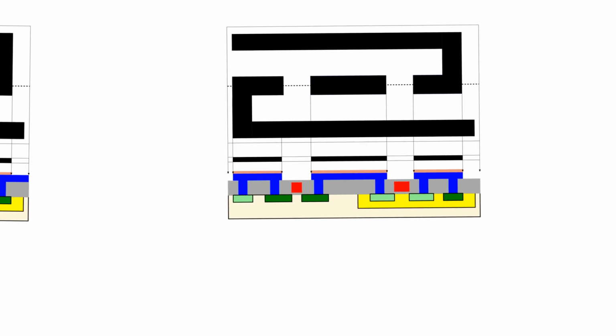We can then use etching to eat away at the metal layers. If we are using aluminum as the metal of choice, then we can use dry etching to eat away the areas that were exposed. Dry etching is actually very good because it is directional, it does not eat laterally, but there's a problem with it in that it builds up a lot of static charge, which could lead to something called the antenna effect. In any case, what we have done here is that we have created metal wire profiles. Here the metal wires are contacting the N plus area of the well.